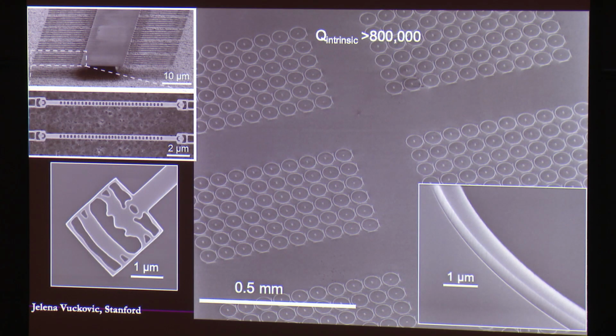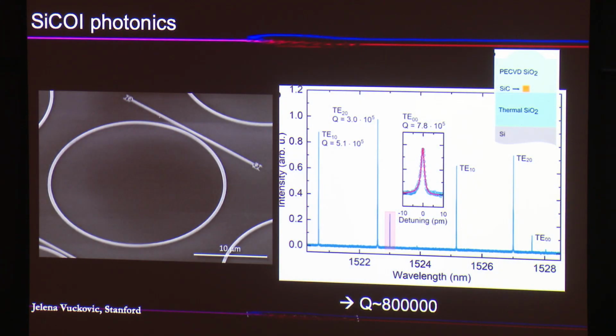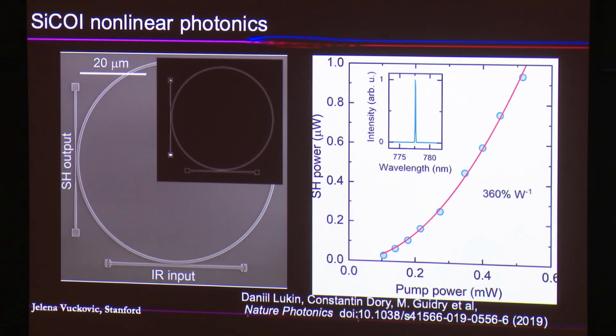We have really high quality photonics, so these are arrays of rings. These are inverse design couplers. Right now we use inverse design, of course, to design all of the interfaces and a lot of photonic structures. We have Q factors approaching millions. Also, we work typically at around 900 nanometers for color centers, but 1.5 micron for photonics. We can also do nonlinear optics.